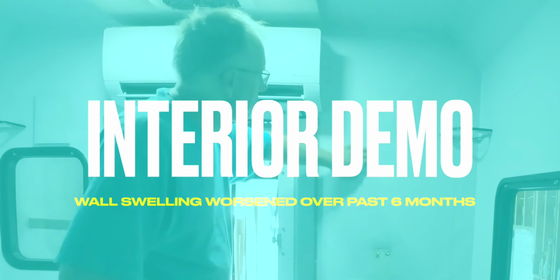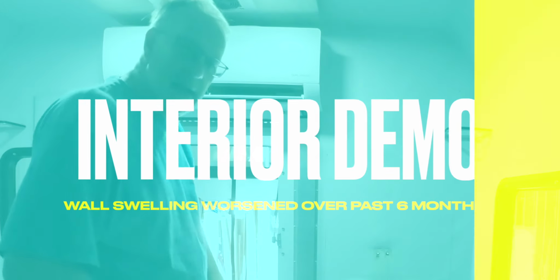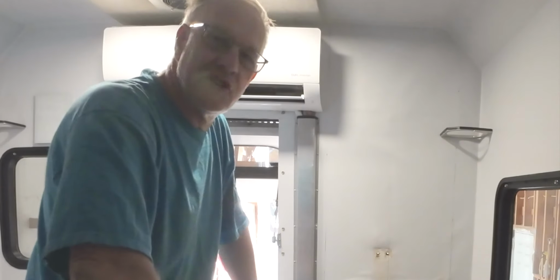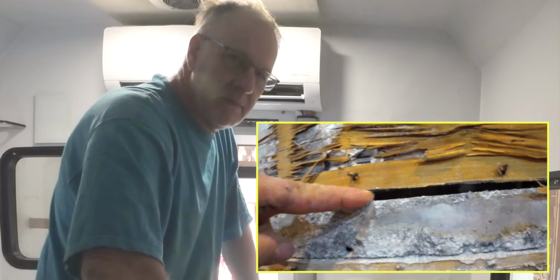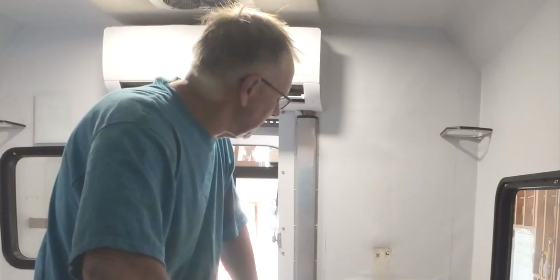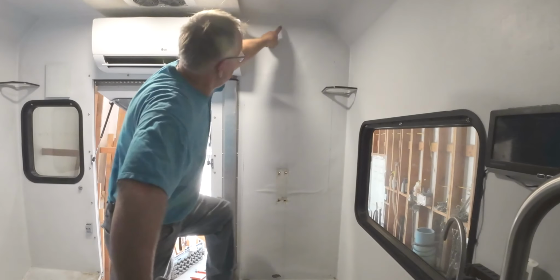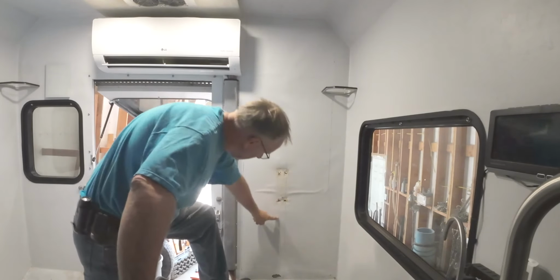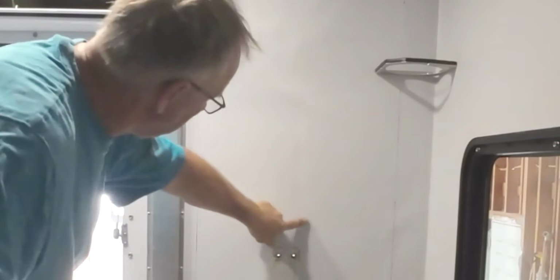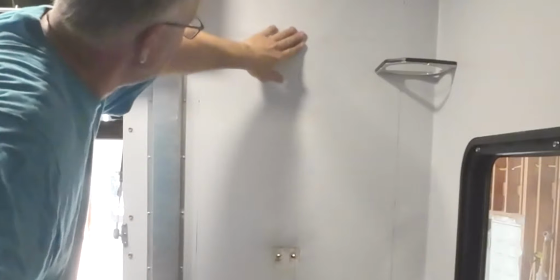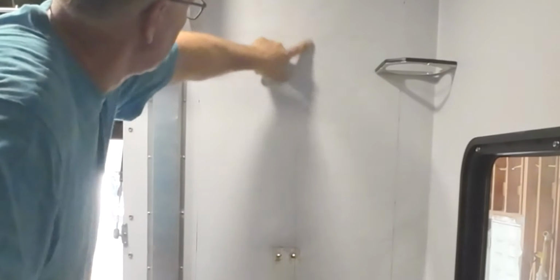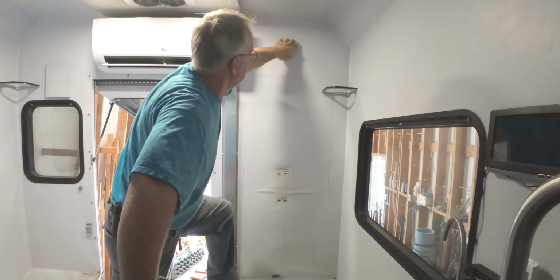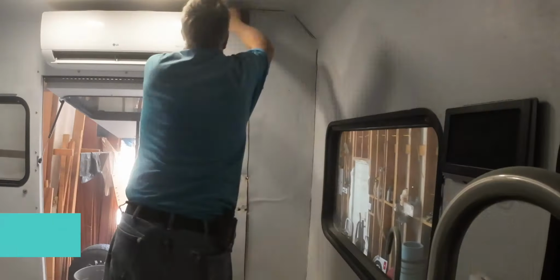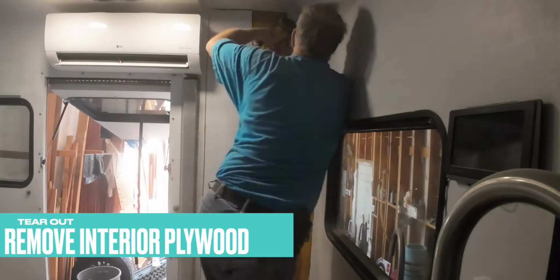And this is the problem that I find after seeing all of the corrosion related swelling that disrupted the board on the outside: I have the same thing on the inside. I saw this earlier. So that aluminum tube runs right down through here, and there's a big bump right here where the two tubes meet, and the fiberglass is loose on the wood all the way up to here. So I suspect that the wood inside of here has been damaged.